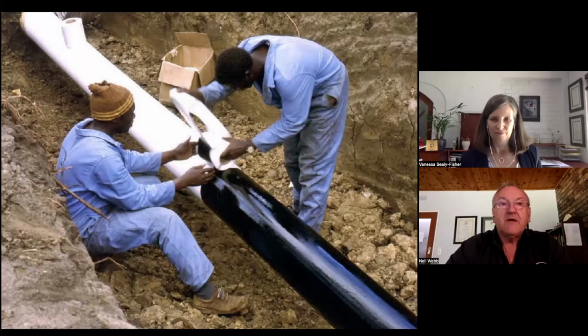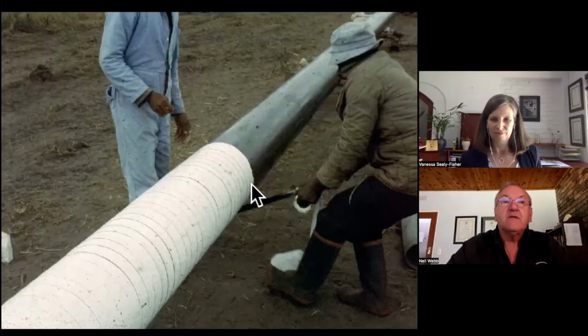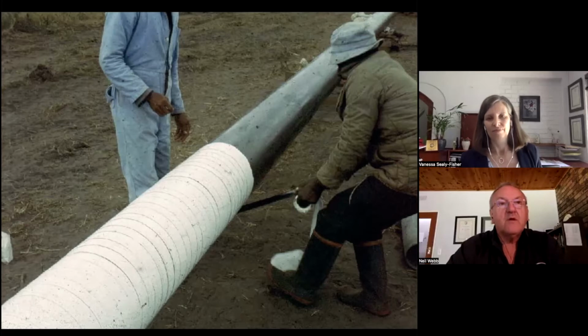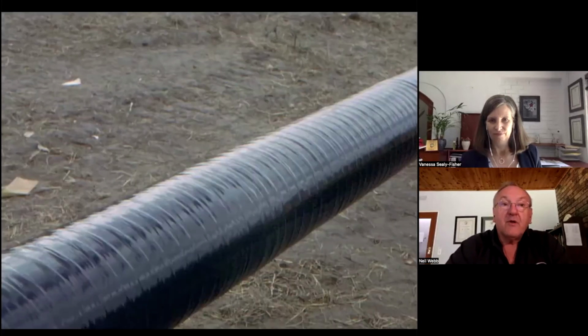In another application, similar tape being used, you can see it's black on the inside, white on the outside. And this is a road crossing that is being prepared to be installed in a cut and cover operation, where the pipe was prepared prior to the excavation, and then the road was closed, the pipe was dropped into the trench, and the road was reopened again a few hours later. This particular operation was a butyl bitumen mastic inner and a polymeric outer.